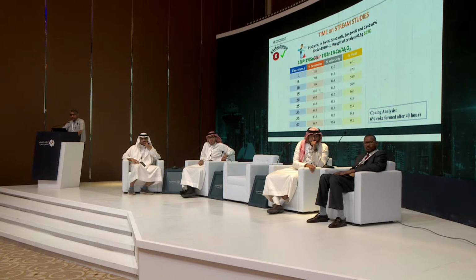And then finally, we conducted some time on stream experiments to see the catalyst stability using our best catalyst, which is 3% indium. I'm reporting this result up to only 40 hours, but we have a study of even approximately 100 hours. This shows that the conversion was very stable, the selectivity in a very good range, and the yield was almost stable in the range of 55. So based on this, we can say that we have a very stable, highly active and selective catalyst for the production of N-butenes from N-butane.